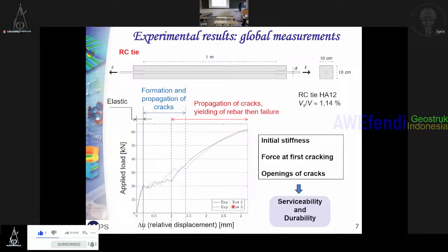For classical measurements, we put here the results: force with respect to the relative displacement between the concrete and the rebar. We have a classical law, an elastic behavior. After that you have the creation of a crack, one crack, or as Dirk Schlicke said, multiple cracks. Then we have the propagation, the yielding of the rebar, and then the failure. In my presentation, I will focus on serviceability and durability, so I will stay in this region.